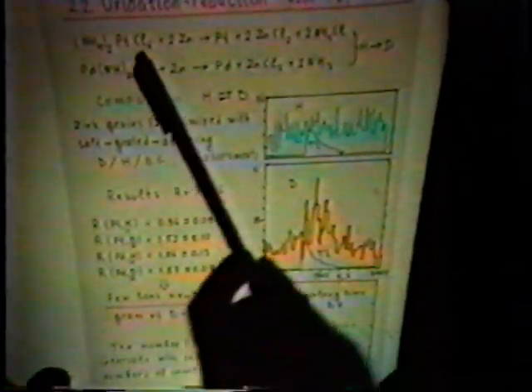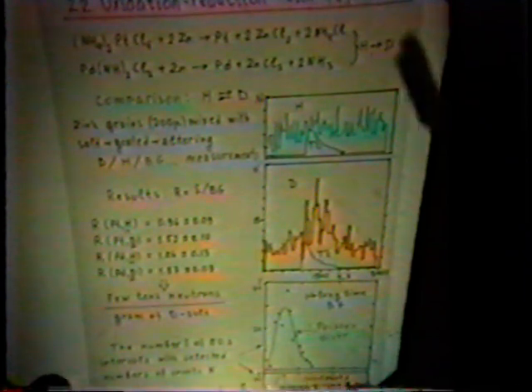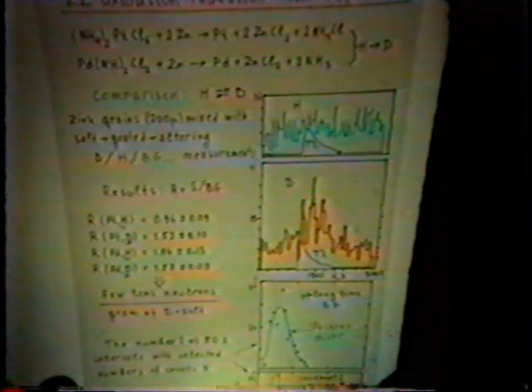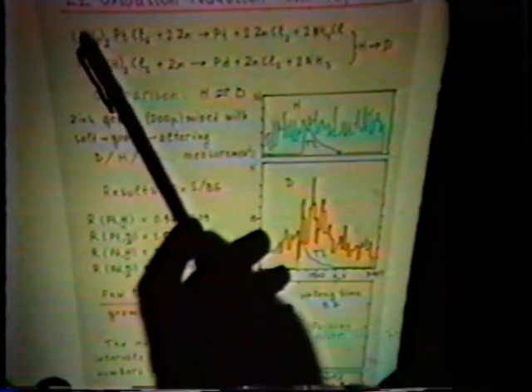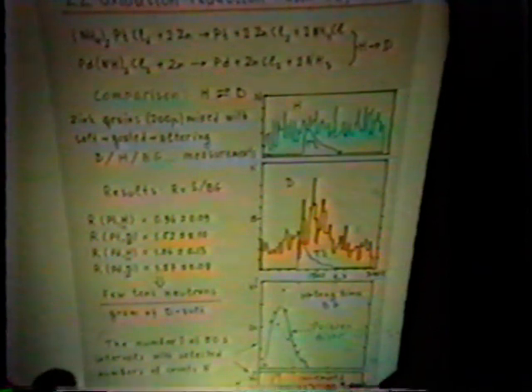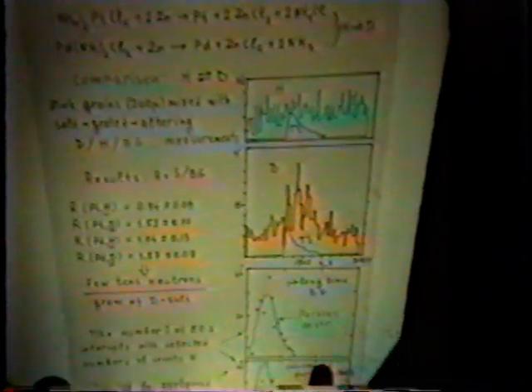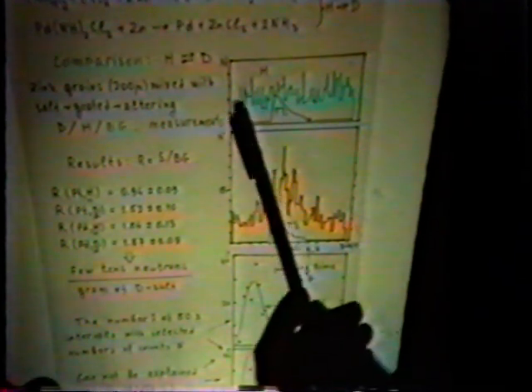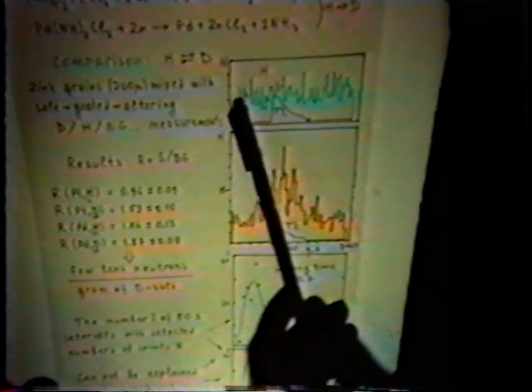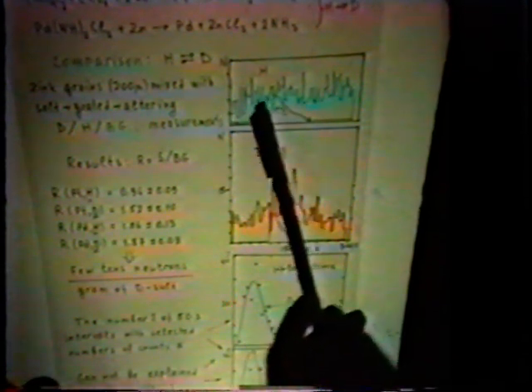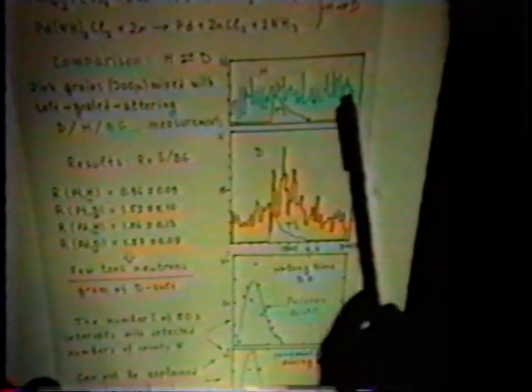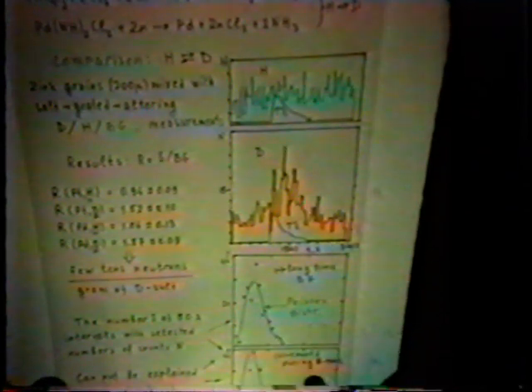The other reaction used by the Novosibirsk group is the oxidation-reduction reaction with palladium and platinum salts. Two kinds of salts have been used, with hydrogen and with deuterium, and they compare the results obtained with these two kinds of salts. Here you can consider these results. Here are the results taken during chemical reactions with hydrogen-containing salts, and this is practically the background level.